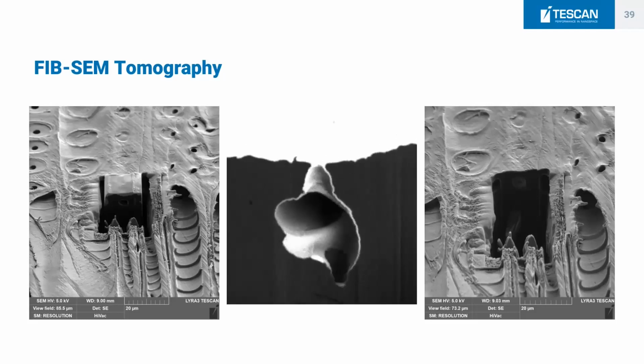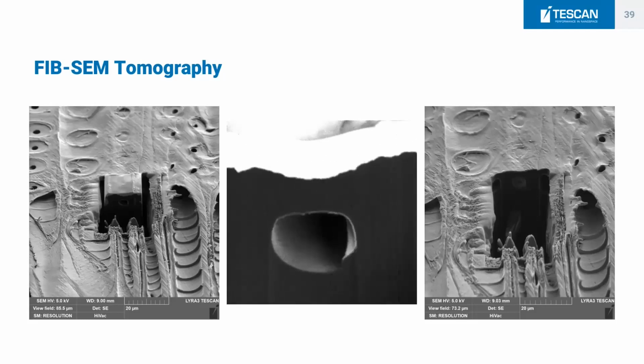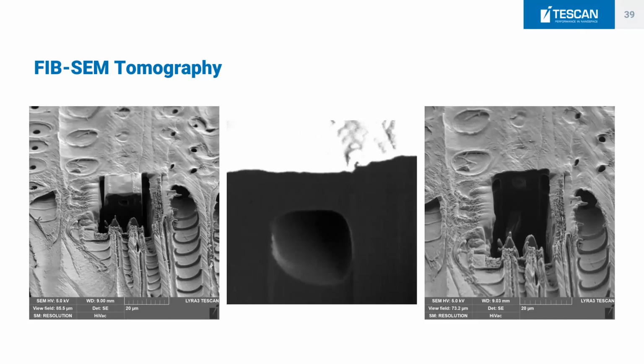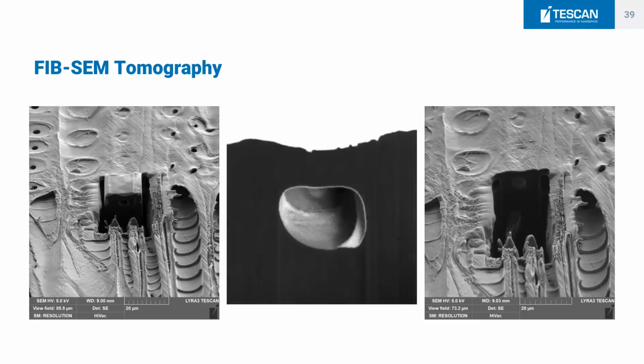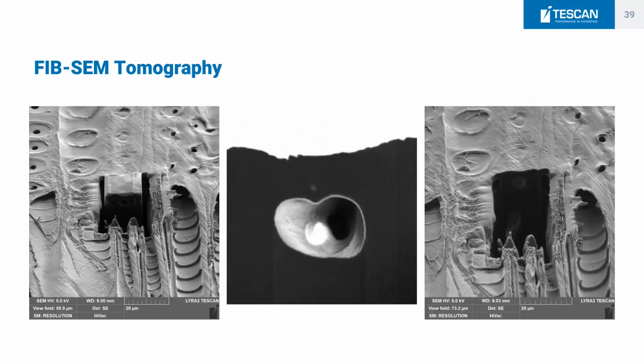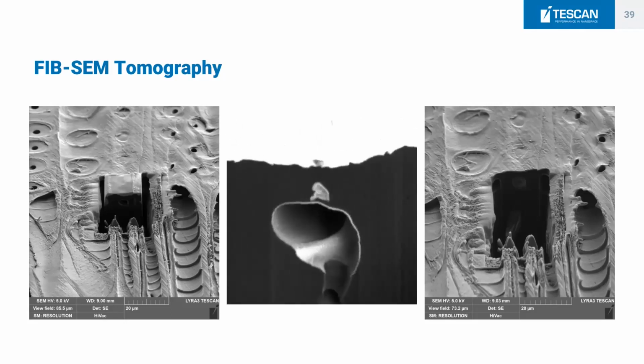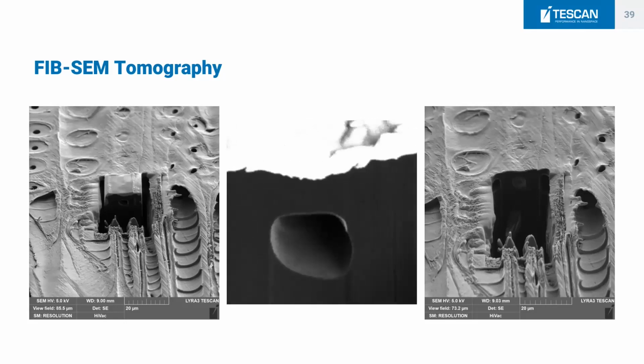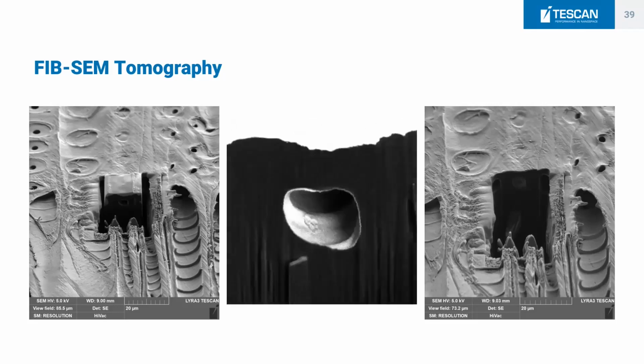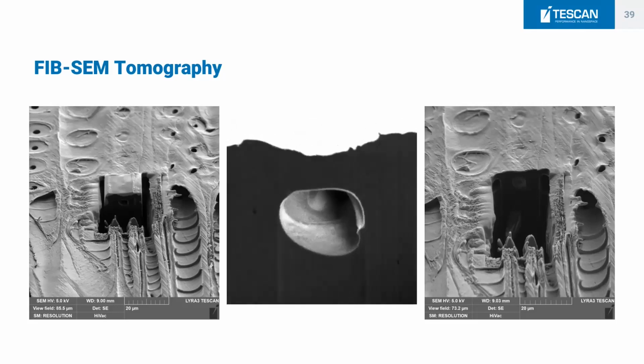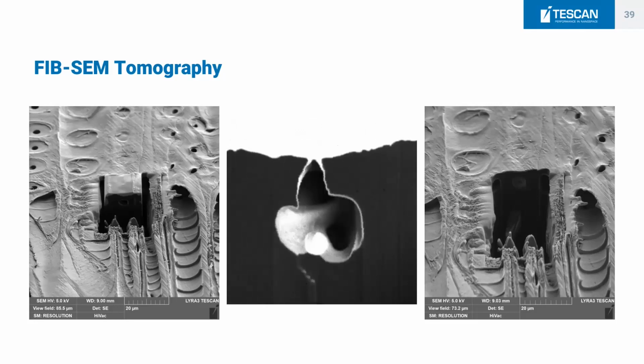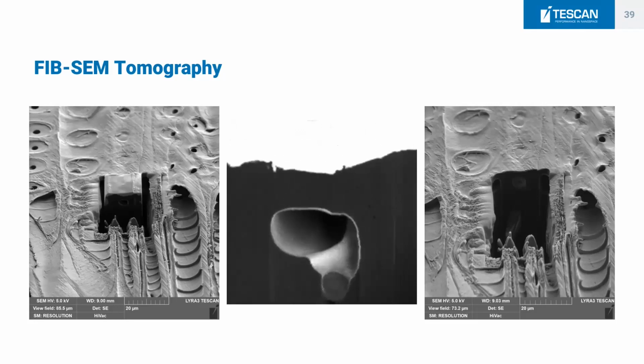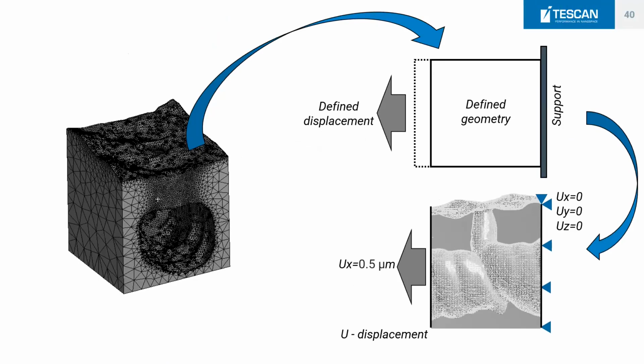So again, there are 2 problems. These tracheids can be very small, so you may not necessarily be able to describe them in certain detail with micro CT. I'm not saying that you can't use a micro CT, but on a small scale, it will probably not always capture the smallest tracheids. So you could use a FIBSEM, do the reconstruction, and apply finite element modeling to this model.